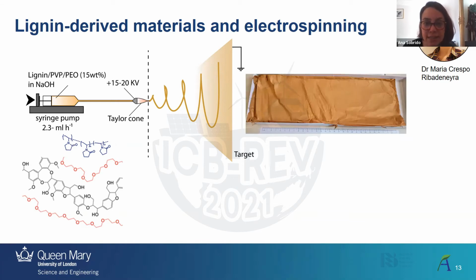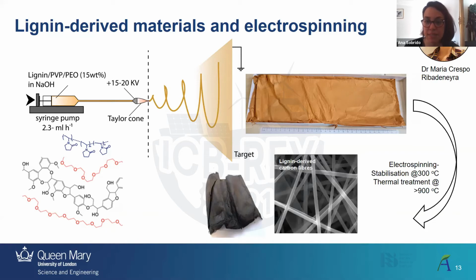We obtain something like this. I think it says there it's like 30 centimeters or so long, which is quite good for the sort of experiments that we want to do. But that's as prepared. Then we need to have a stabilization treatment at 300 degrees C, and then a thermal treatment at 900 degrees that makes those as-spun fibers become a highly porous conducting electrode that is also freestanding. And this is going to be a very good advantage of these materials.